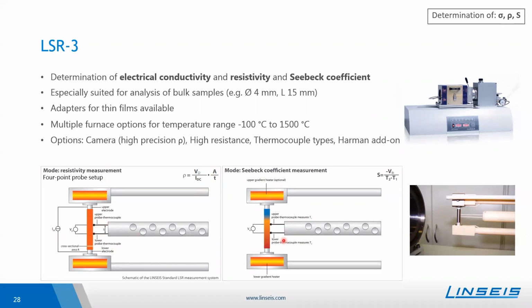As mentioned, the LSR3 can also determine the Seebeck coefficient. Here, the same setup is used. However, one does not impose a current into the material, but one creates a temperature gradient over the sample. For that, in the lower electrode, there's also a secondary heater, which creates then this temperature field along the sample. And with the probes, we determine then the thermal voltage, which results from that.